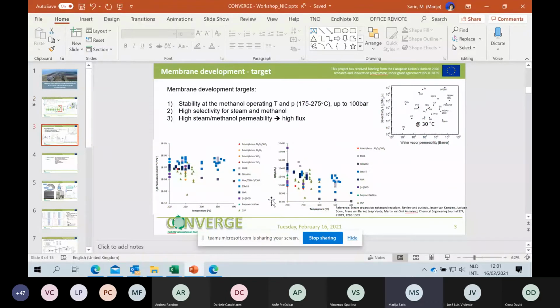And we need to develop membranes that are stable at operating conditions for methanol synthesis. So temperatures between 175 degrees and 275 and up to 100 bar. We need to have a high selectivity for steam and methanol and high steam and methanol permeability.